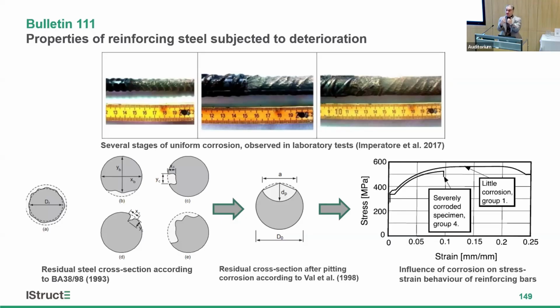So essentially the ductility is reducing, and also the strength. The reason the strength is changing is because, whatever we do, we cannot calculate the exact area. So that's why we tweak the yield strength with a coefficient, we call it the pitting coefficient. So we reduce the area and then we add the pitting coefficient to account for this. Some of these recommendations are in this existing bulletin, and there is more detail coming up in the future bulletin.